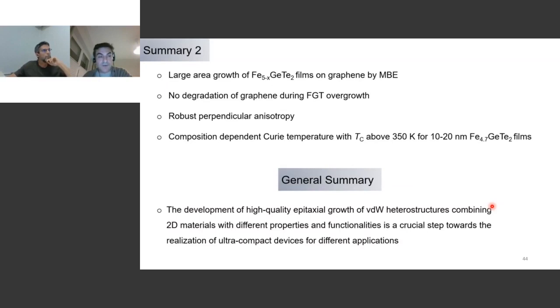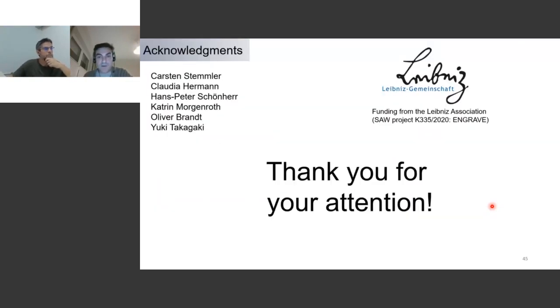Graphene is actually not degraded during growth, which is good news, because you still want to use graphene as a functional material there. And it's nice to see that you can modulate, for instance, the Curie temperature by manipulating the composition of the films. And with that, I just want to make a general summary: the development of high-quality epitaxial growth of van der Waals heterostructures combining these two different 2D materials is a crucial step towards realization of new types of devices. So thank you very much for your attention, and I'm very sorry for extrapolating the time by, I don't know, 5 to 10 minutes.